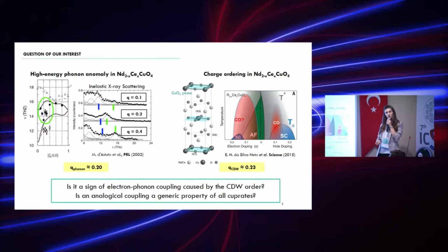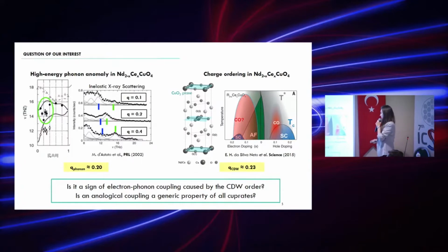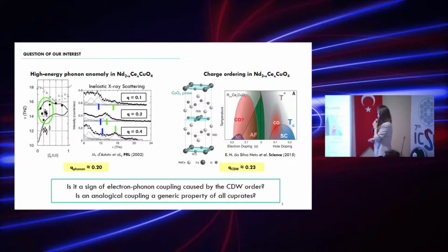A similar wave vector at which QCDW was also reported in 2015. So the question was, is it true not only for a striped system, but also for a very simple cuprate, that the phonon softening can appear because of the presence of charge density wave order? Is it a generic property of all cuprates? Is it a generic electron-phonon coupling? And this motivates us to perform our studies.